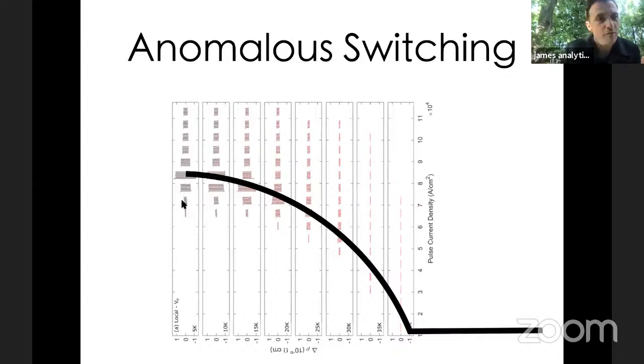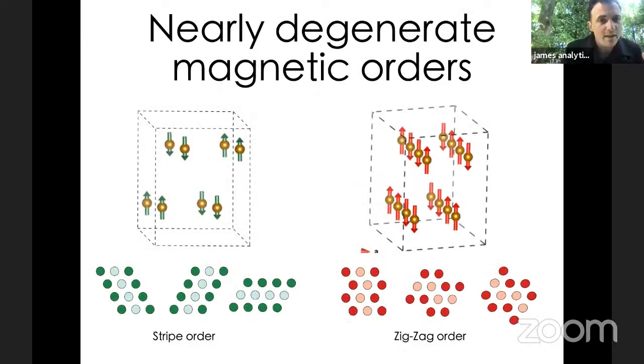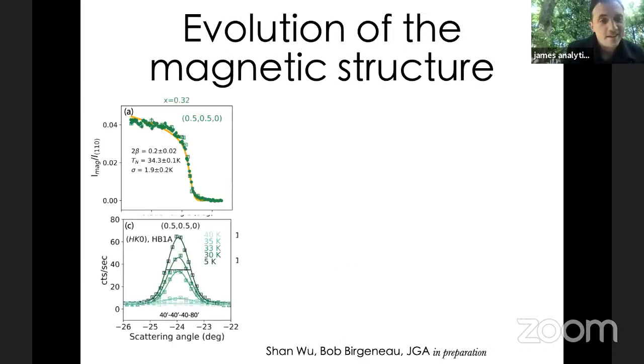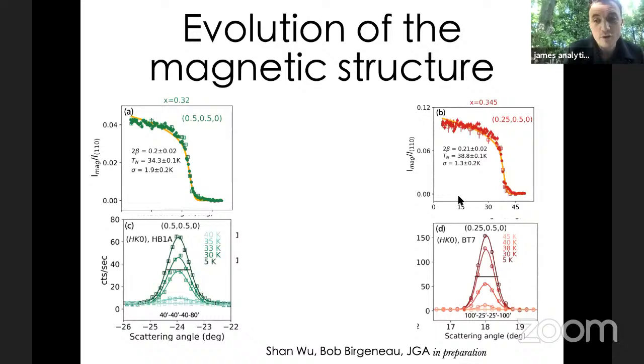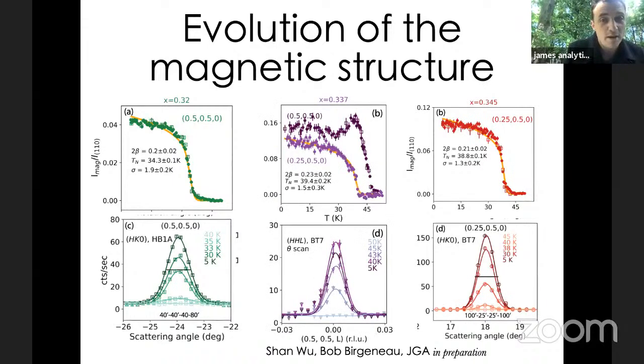But why would you have opposite kinds of behavior between one intercalation and the other? Well, the controversy in the literature was between two different kinds of magnetic order, both anisotropic. One of them is stripe order, and the other one the zigzag order. The zigzag order was the one determined in the early 70s by Rietveld. The stripe order was a more recent determination by another group in the 90s. And we wanted to get to the bottom of which magnetic order was actually in the system. Well, you can guess that it's both. In the underintercalated, it seems that the magnetic order is dominated by the stripe-like order. In the overintercalated, it seems to be dominated by the zigzag-like order. And in the stoichiometric compounds, you turn out to have both order parameters involved.